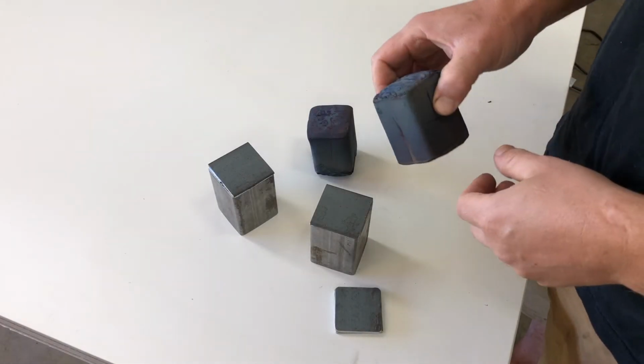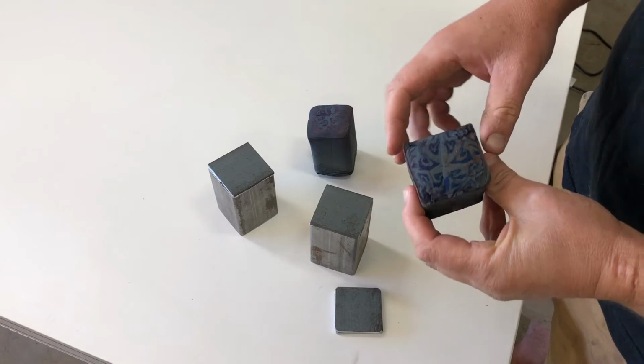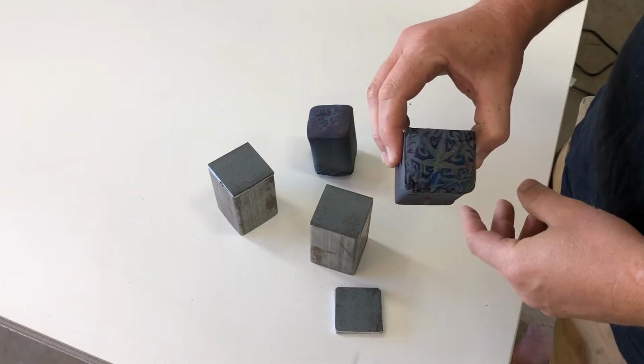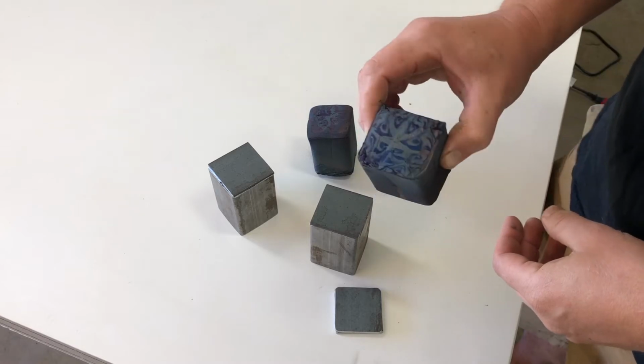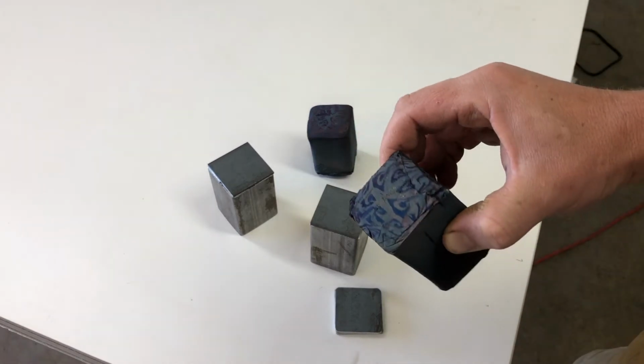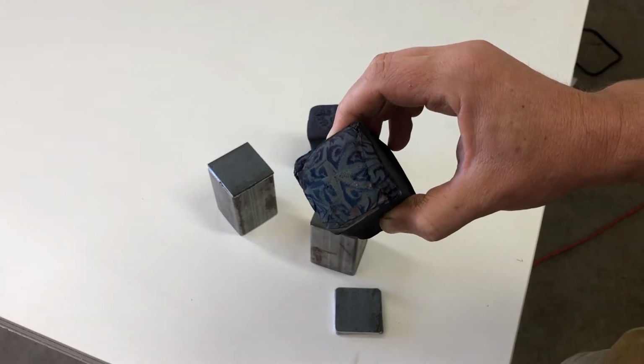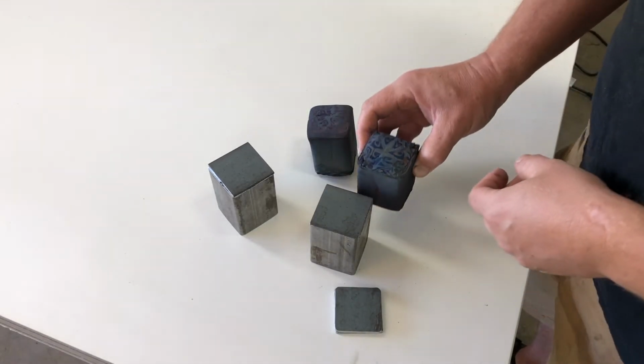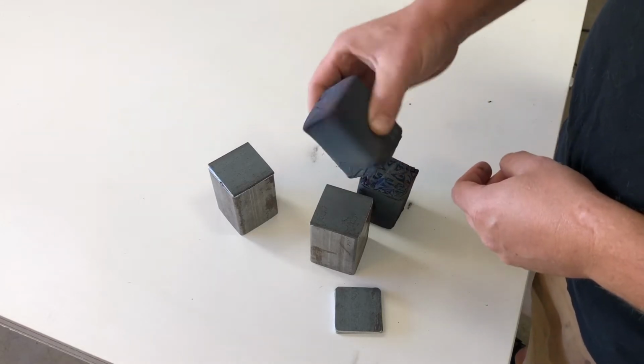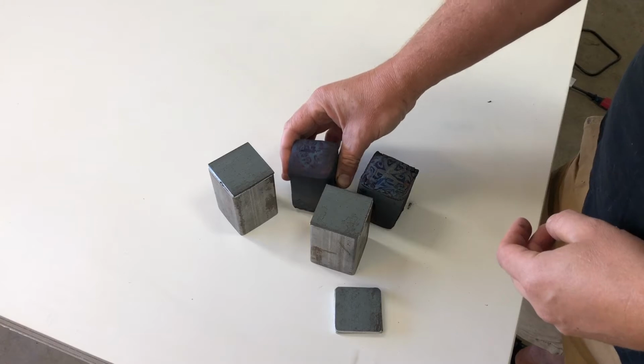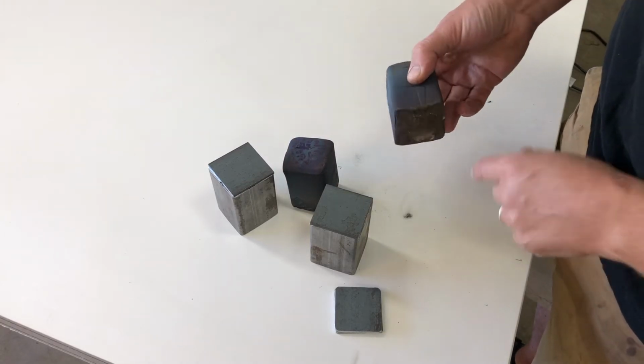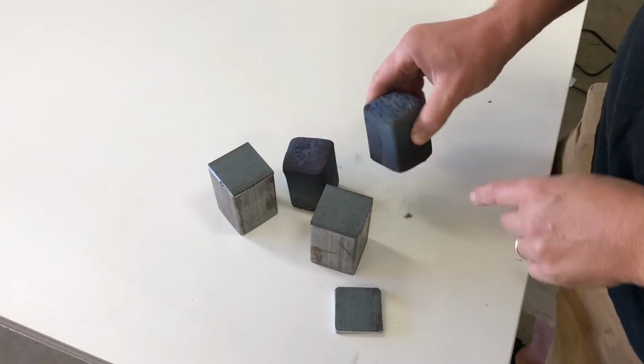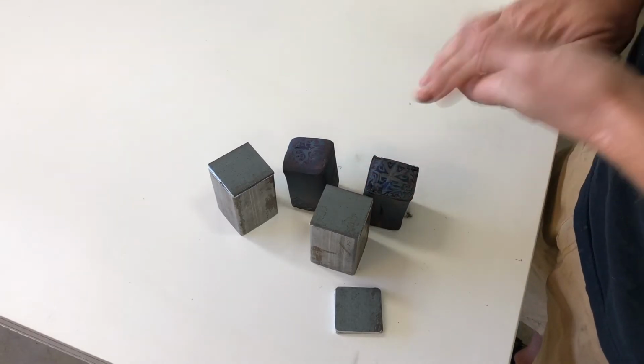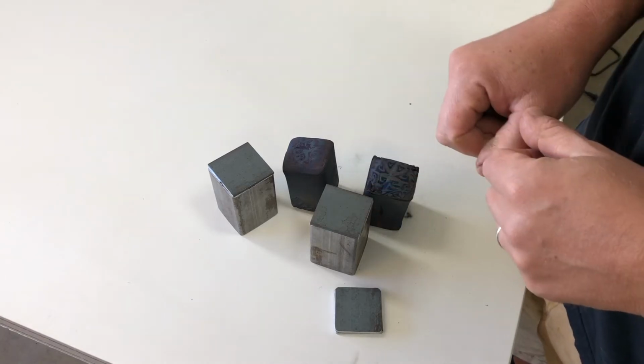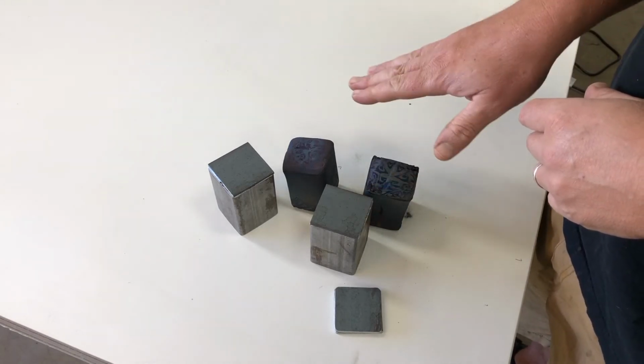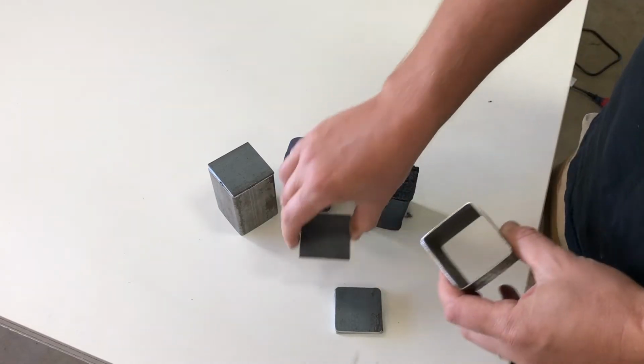So as part of a little experiment here, I actually baked my 2 blocks up to about 450 Fahrenheit. You can see definitely got some temper colors going on, which does show up our pattern a bit better. But I was doing this to see whether there was really additional shrinkage at that temperature. And quite honestly, there's not. I do get a little bit more powder off the outside though. So I would suggest sticking to the 250 degree Fahrenheit bake before loading into the canisters.